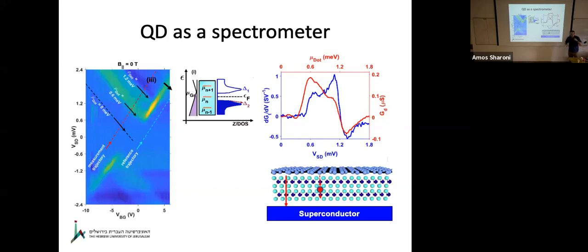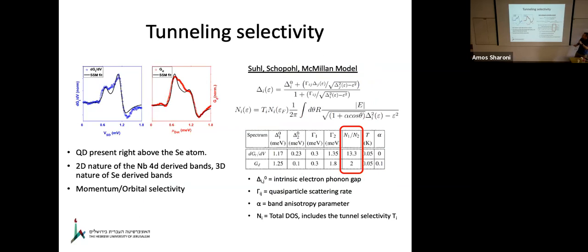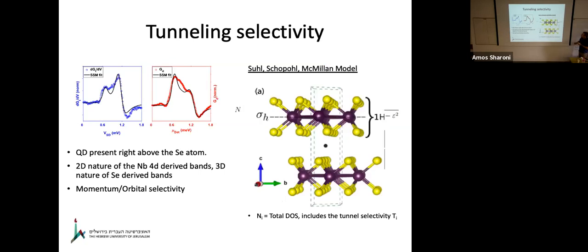That means that the dot undergoes some kind of selection rule when it couples to the superconductor, and Davidas has spent a lot of work trying to figure out these selection rules, showing that the dot actually favors the lower energy band, which we know is a selenium band. Now, one possibility is that the dot resides geographically just above a selenium atom, which is here.